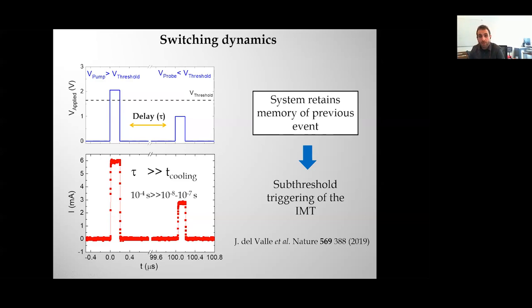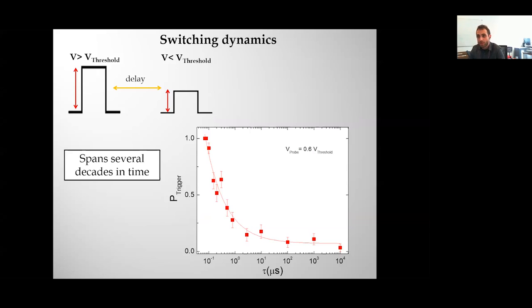To understand better this type of memory, this volatile memory, we did a systematic study. One of the things we did is change the delay time between these two pulses. This is what you see here. The second pulse is 60% of the threshold voltage, and you see the probability that it will trigger the transition as a function of the separation between the two pulses. As you separate the pulses more and more, this probability goes down, but this is a logarithmic scale, so it goes down very slowly. At 10 milliseconds, which is 6 or 7 orders of magnitude longer than any thermal timescale of our device, you still have about a 5% chance to induce the transition.